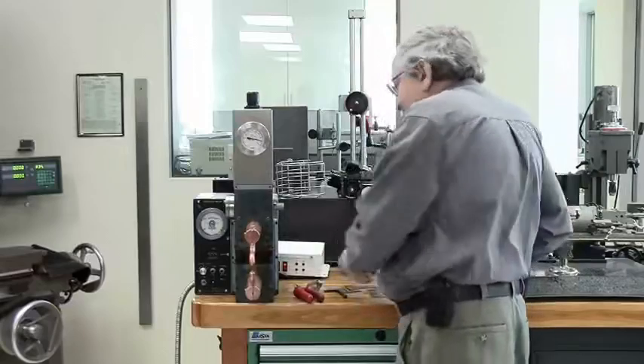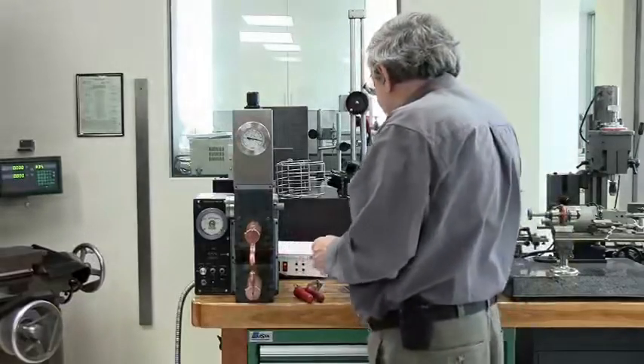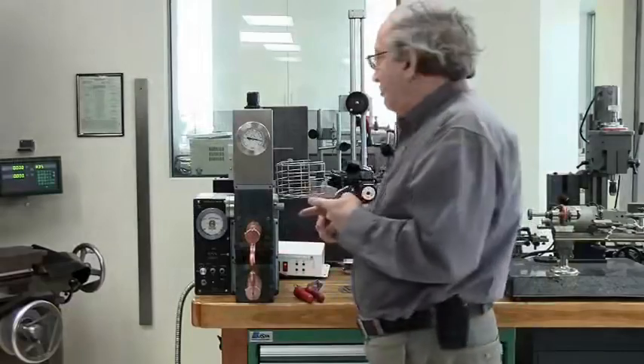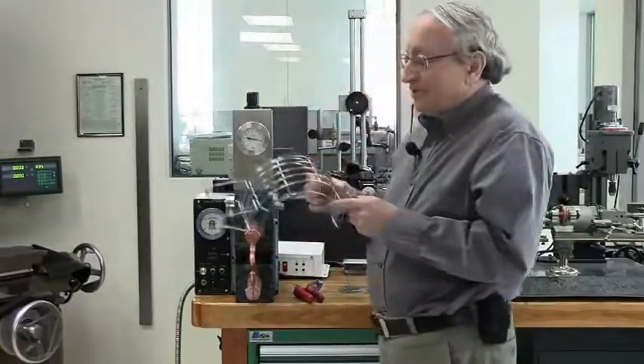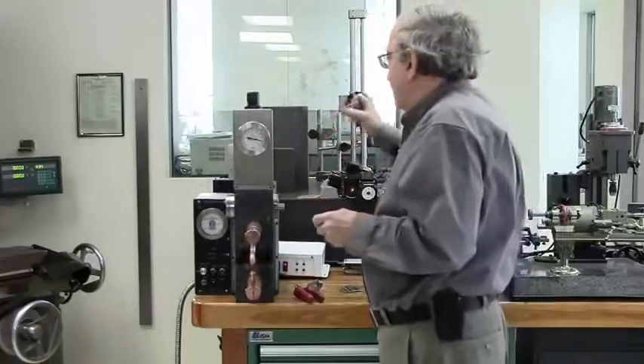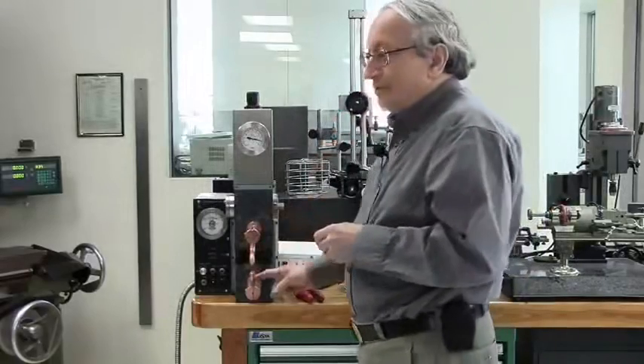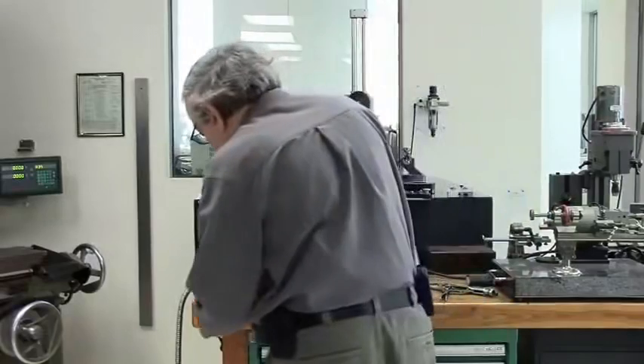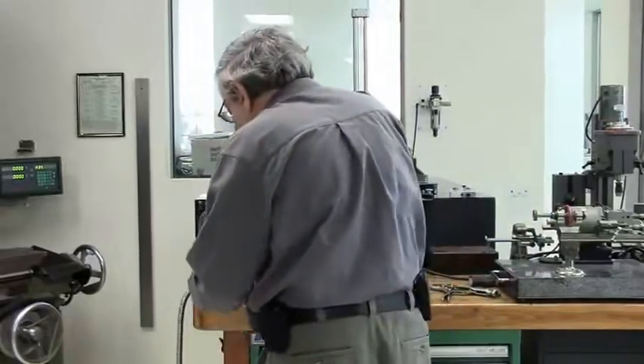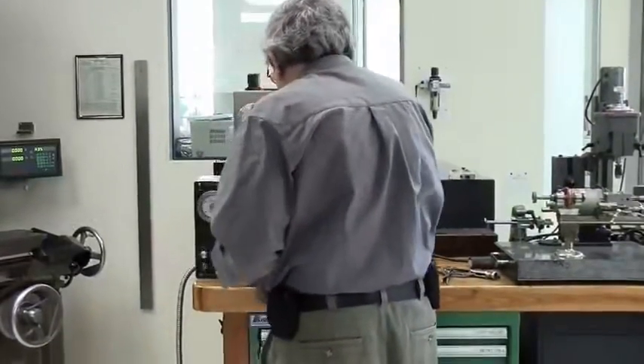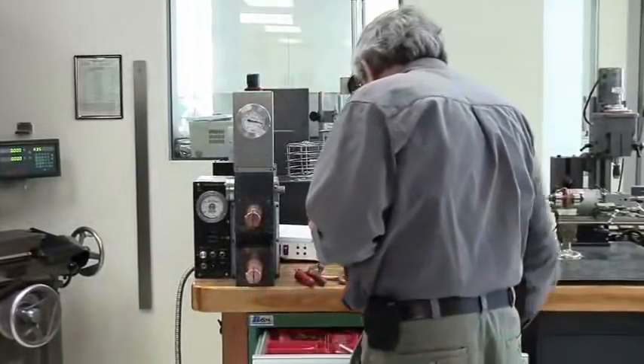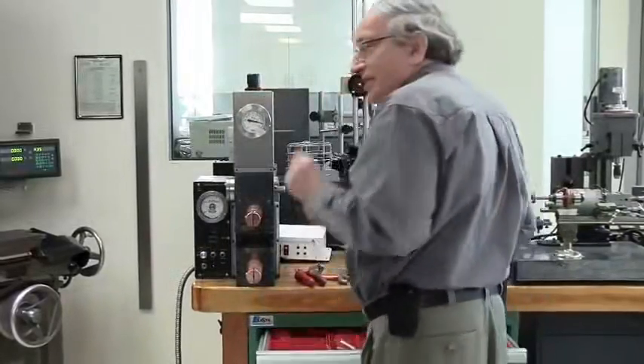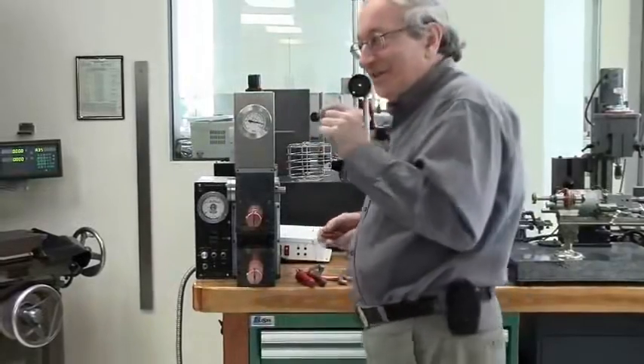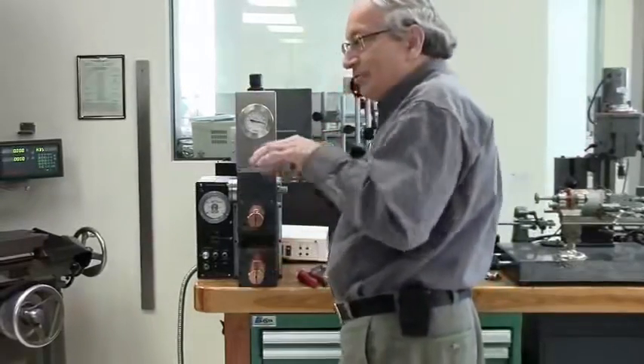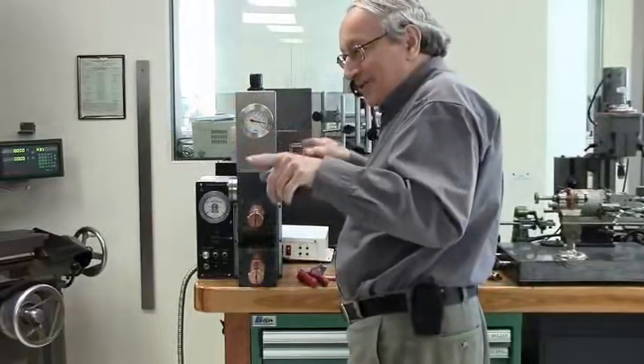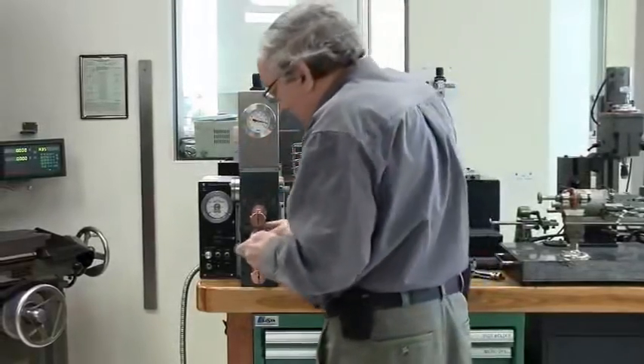Now, what it welds very well is rods. So if you want to make something like this, which is made from wire, it's ideal, and you can weld a 1/2-inch rod to a 1/2-inch rod with this. So it's actually very efficient on rods. One reason for that is that when you weld 2 rods, you have a very small contact area, and because you have a very small contact area, you have very high current density. And the heat cannot escape in 2 directions, it can only escape in 1 direction along the rod. So the welding is much more efficient.